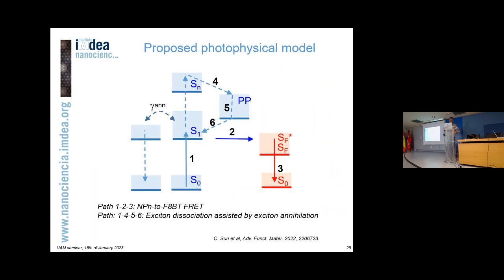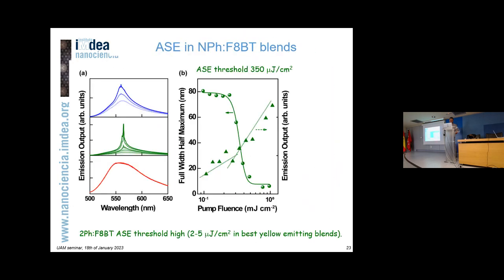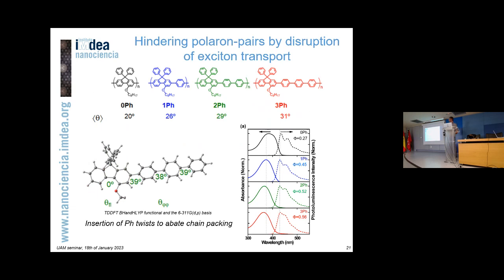One modification that we normally do is, for instance, to exchange the aryl chains by t-Bu substituents. That makes a more robust system than what we would effectively have.